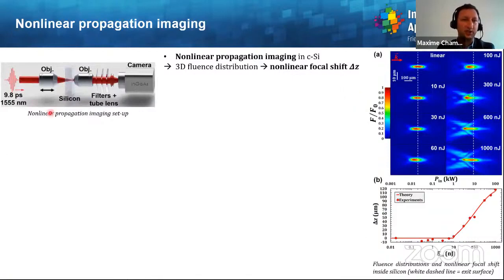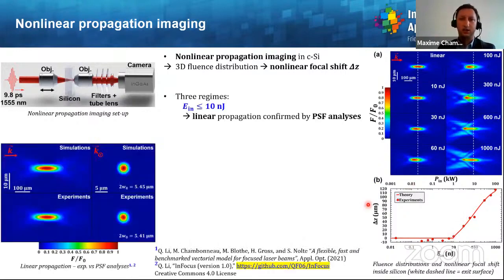We imaged the nonlinear propagation inside silicon by means of this setup, which is nothing else than an inverted microscope. It allows us to evaluate experimentally the 3D fluence distribution inside silicon for different input pulse energies indicated here, and thus the nonlinear focal shift delta Z as shown here as a function of the input energy. In this data, 3 regimes can be distinguished.